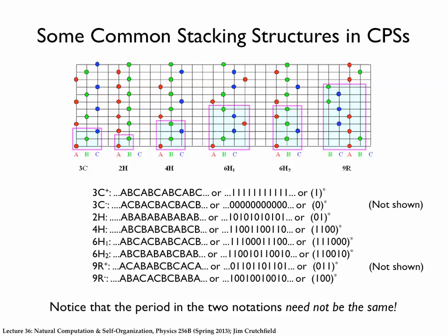And something that we call the 9R, even though in this notation, the Hägg notation, it just goes 011, 011, you'll notice that if I go 0, then 1, 1, when I stack the next layer, I've sort of had a rotation from the bottom layer to where I start the next one. So I have to go through three cycles of this to get back to the original layer, to get back to the original orientation, the absolute orientation of the bottom layer. And so that's nine layers I have to go through, and that's why we get the nine. So this notation actually turns out to be much more compact and, I would argue, more useful.